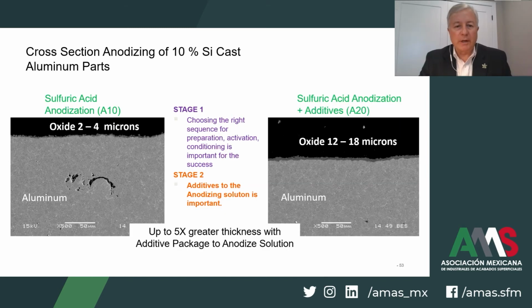In this slide, we're showing a cross-section photomicrograph of a 10% silicon intermetallic cast alloy that doesn't have any special processing. So you can see on the left side, the anodic oxide can only reach 2 to 4 microns. For the right photomicrograph, the cross-section shows an anodic oxide from 12 to 18 microns simply by incorporating the stage 2 processing with the additive package for the anodizing electrolyte. In this case, we see up to 5 times greater oxide thickness compared to using no additive at all.